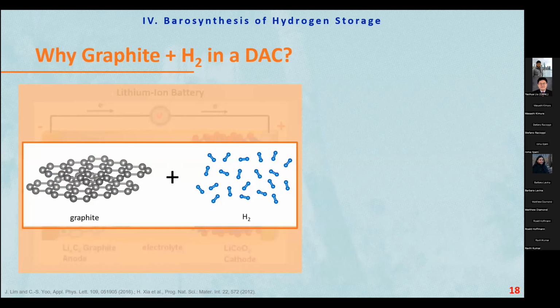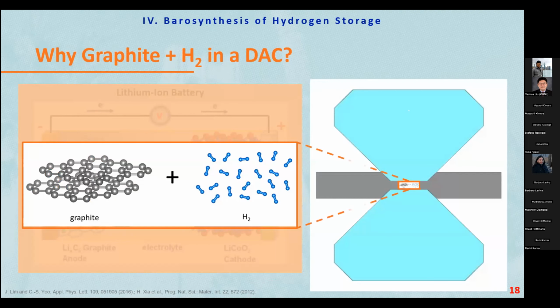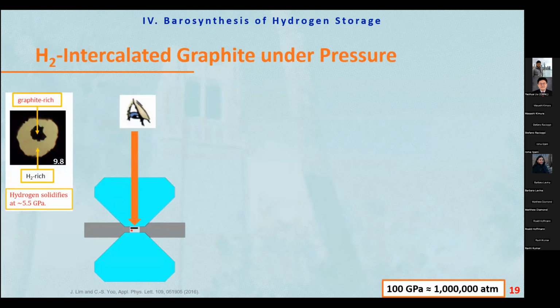That's kind of simple, that we can do with the high pressure gas loader, and we put the graphite and hydrogen mixed together in the diamond anvil cell, and did the measurement. And this is the result that you are seeing. The picture has a graphite rich region and a hydrogen rich region, the bright area. Graphite is dark, and this is 10 GPa. At this pressure, the solid hydrogen is already solidified, above 5.5 GPa. And graphite in this case is very thin, 1 micron thick.